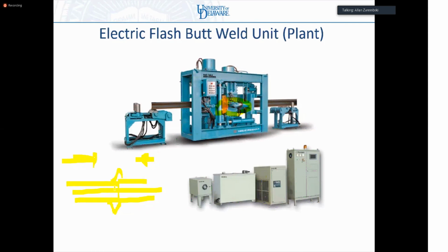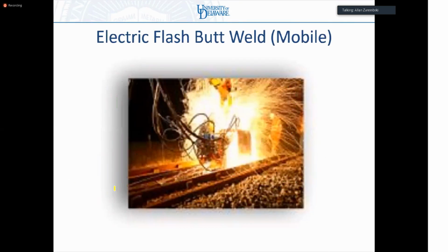So if I make 20, 30 welds in a row, over that point of time, I may have lost a meter or certainly 20, 30, 50 centimeters of rail. And then I have to replace that. I have to add that rail in at some point in time to ensure that I have enough rail for continuity. Electric flash butt welding process is more expensive, more difficult, but stronger than the thermite weld.